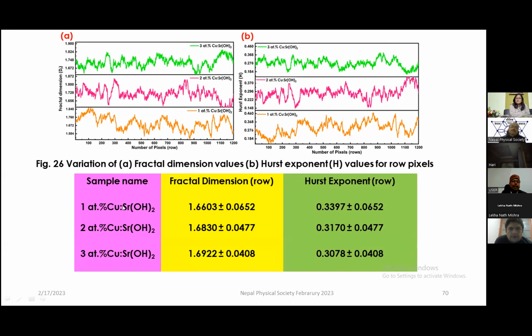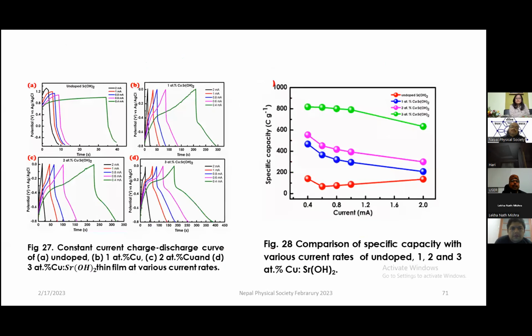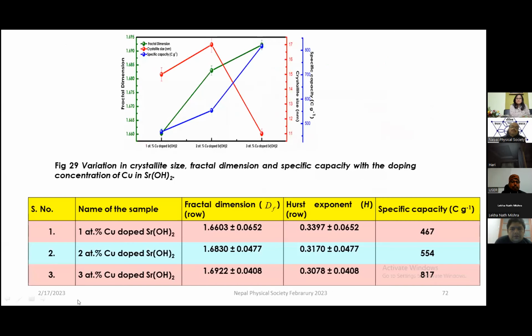So we applied it and we obtained for our sample, one can see, 1 atomic percent, 2 atomic percent, 3 atomic percent. And it has been observed experimentally that 3 atomic percent of the copper doped strontium hydroxide has the highest value. So here also we are getting the highest fractal dimension. So this is the comparison, and one can see it here.